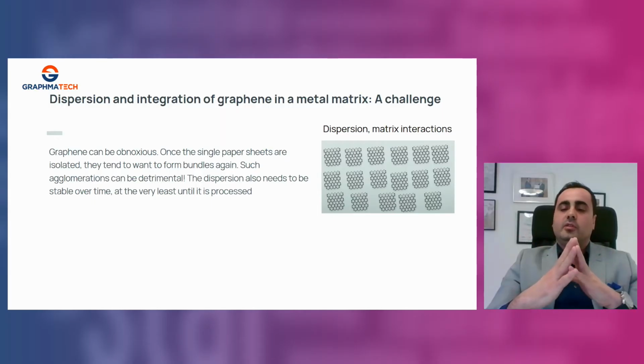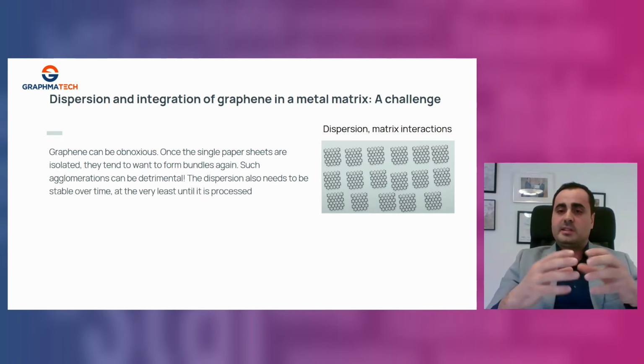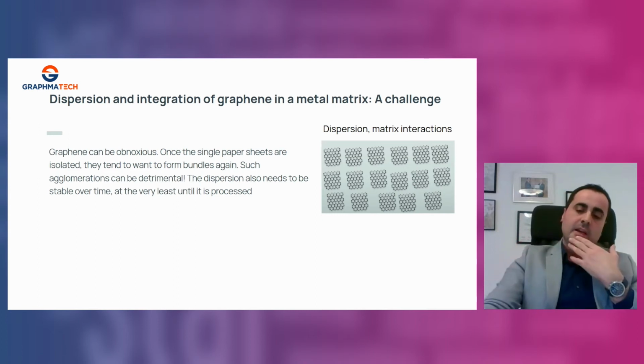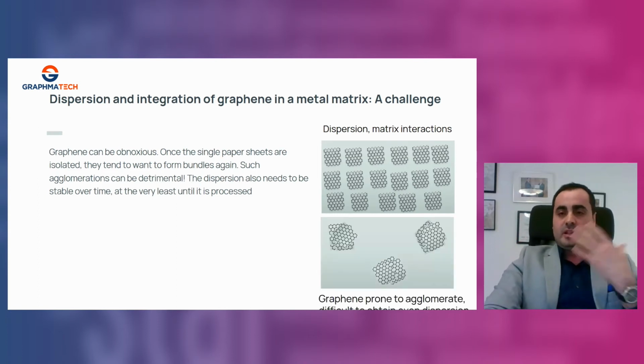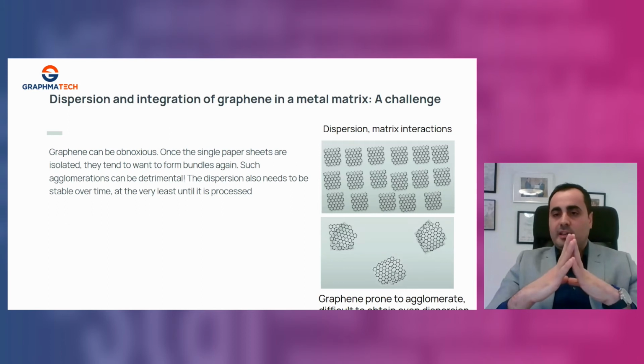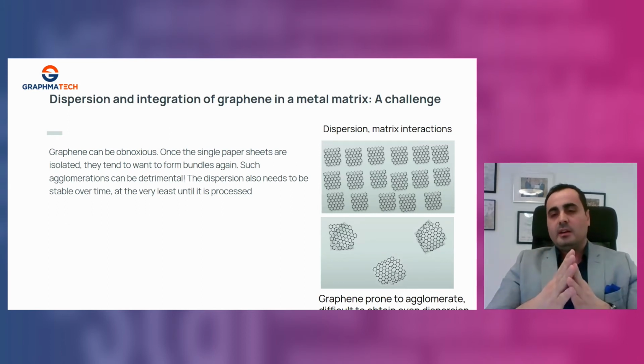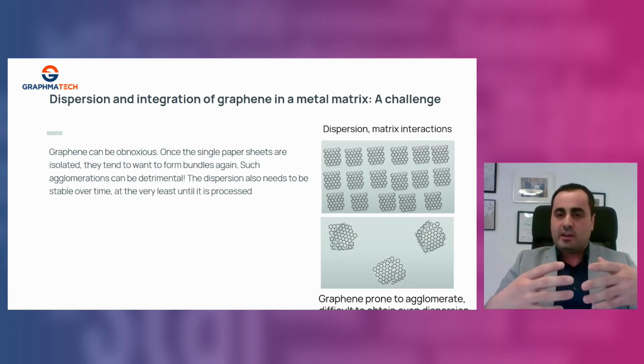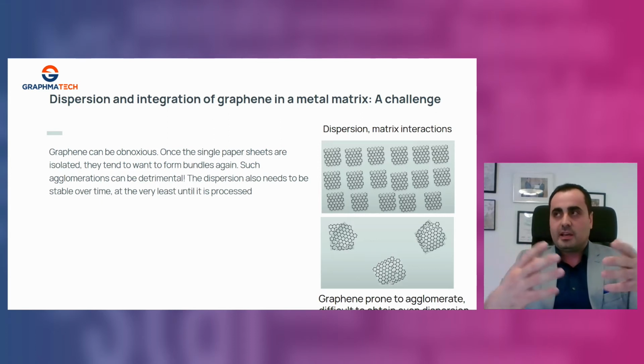So, of course, in the ideal scenario, you have a matrix, you have nicely distributed additive, you have isotropic material. Wow, that's fantastic. And then you start to get very good properties based on the graphene addition. However, the reality, as you know, in many cases, is never the case. You get these additives to agglomerate and to stack together. And then you have a lot of free matrix where you don't have access to graphene. And then, okay, it's just like a metal.